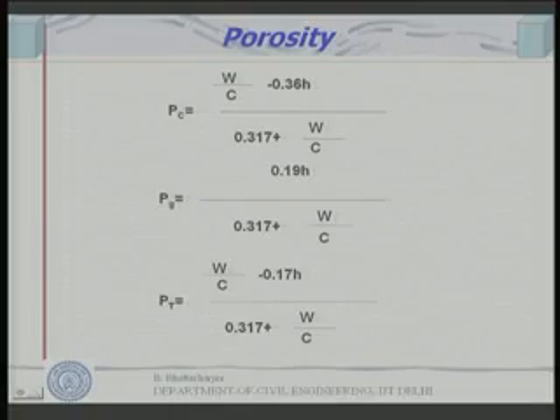And total porosity again is a function of water cement ratio. So the higher the water cement ratio, the higher your total porosity. The denominator is the same everywhere, 0.317 plus W by C. So the higher the water cement ratio, the more the capillary porosity and the more the total porosity. The higher the degree of hydration, the more the gel porosity. But as I said, gel porosity does not really contribute to poor performance with reference to strength and durability. It is mainly the capillary porosity which governs the strength and also durability properties of cement based systems, and right now we are looking at cement paste. We can extend this idea to concrete sometime later on.